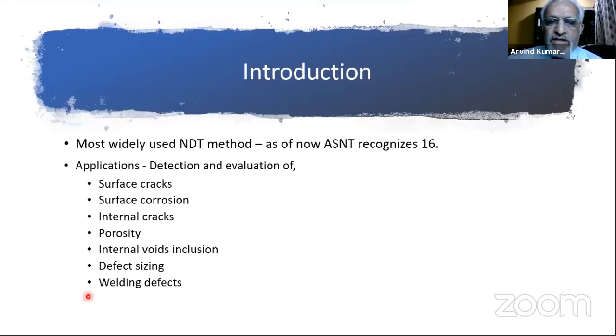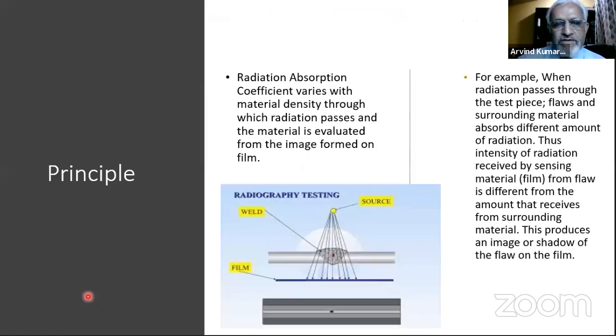Now here we can detect all kinds of defects which are there in the welds, like, even if the intention is not to see the surface corrosion, if at all there is something, it can be detected. Then you have surface cracks or internal cracks, porosities, lack of fusion, and all these kinds of welding defects can be detected by the radiography method. Now in comparison to UT, it is easier to detect three-dimensional defects in radiography, and two-dimensional defects are difficult to catch in radiography. Like very tight cracks, you may miss them in radiography, whereas you may not miss them in ultrasonics.